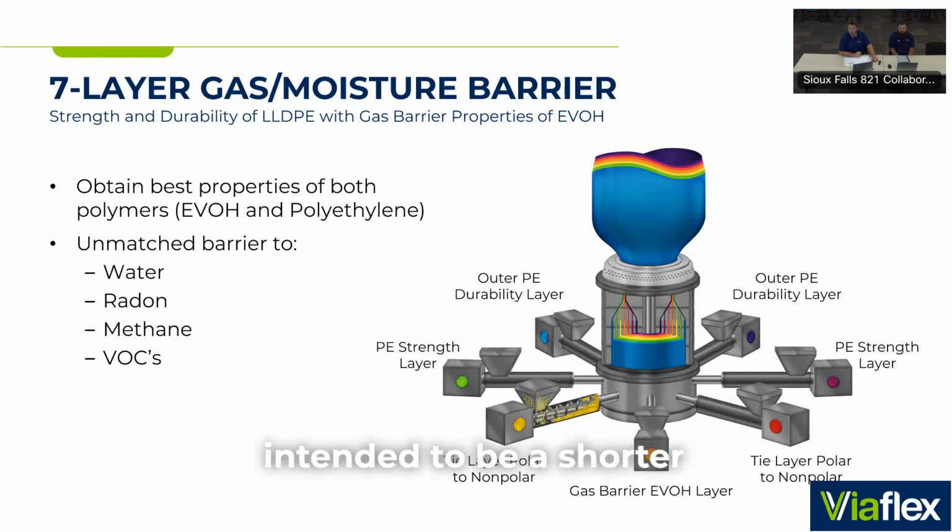This was intended to be a shorter study, but it ended up taking about 6.5 years to complete, and I'll explain why. This slide depicts a little bit of the methodology. The picture in the bottom right is one of the chambers that was designed and built to test this. On one side of the chamber, you would have a reservoir of an aqueous solution, in this case trichloroethane, which is what the graph represents. And on the other side, you would have just a distilled water reservoir.